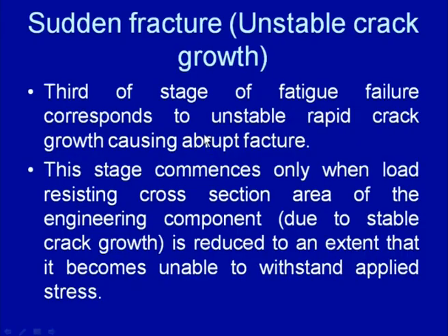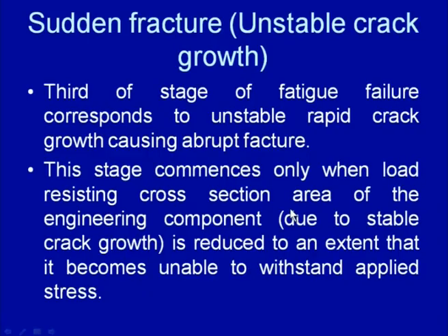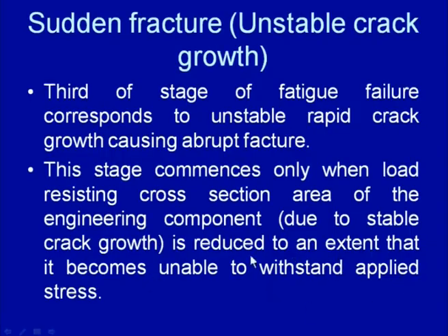Then the third stage, in which a very unstable crack growth takes place. The third stage of the fatigue failure corresponds to unstable, rapid crack growth causing abrupt fracture, and this stage commences only when the load-resisting cross-sectional area of the engineering component is reduced to a great extent. This reduction in cross-sectional area occurs due to the stable growth of the crack in the second stage, and when this reduction takes place to such an extent that the component becomes unable to withstand the external load, sudden fracture takes place.